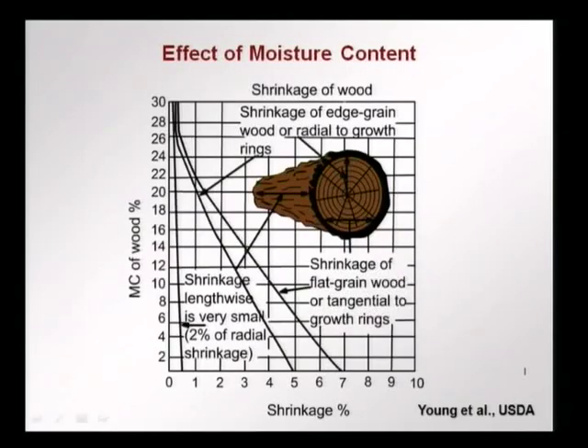So this again shows you how shrinkage occurs as a function of the moisture content. On the y axis we have the moisture content as percentage in wood, and on the x axis is the shrinkage. So we find that as the moisture content decreases, that is we are drying the wood, we can have shrinkage in the tangential direction which is quite high, followed by shrinkage in the radial direction. In the longitudinal direction, shrinkage is very low. So this is the amount of shrinkage as a function of moisture content, and as the wood is drying, the moisture content is dropping and the wood experiences an increase in shrinkage. And what we see is that in the longitudinal direction, along the grains, along the fibers, shrinkage is very low, but in the other directions you can have significant shrinkage, and this should be kept into account when we are looking at the dimensions.